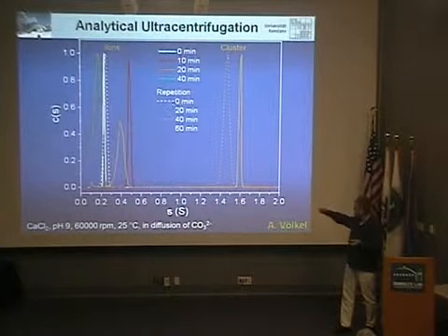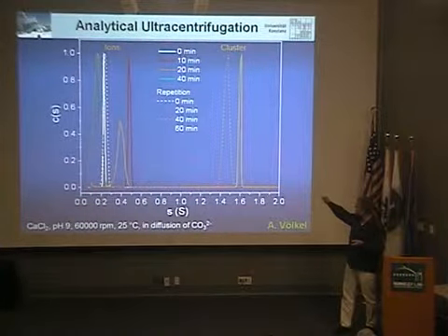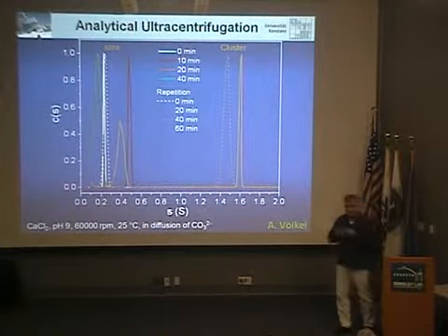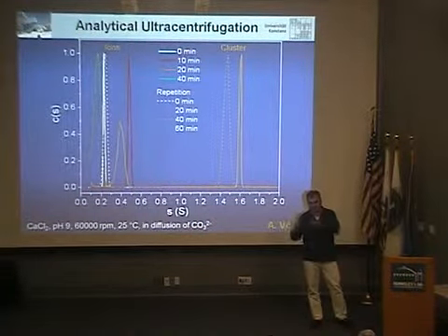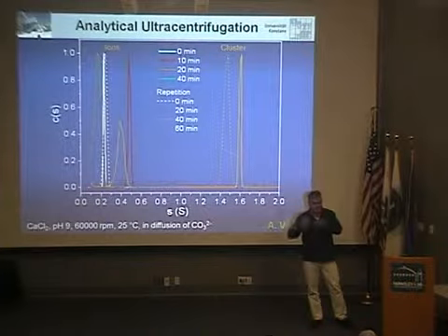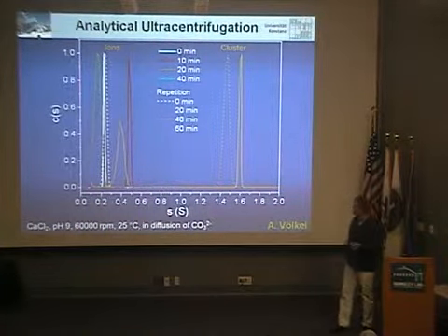And you can repeat that experiment. That's the dashed curves. And you get the same finding again. And you see a little experimental variance because it's at the limit of the centrifugation. Because if you really think about the experiment, we are separating ions from something which is not much bigger than ions. So that's even at the limit of an analytical ultracentrifuge.